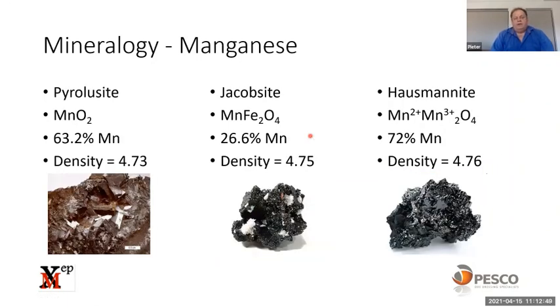Mineralogy for manganese is quite interesting. You've got 3 different types of manganese: pyrolusite, jacobsite, and hausmannite. What's interesting is there's a significant difference in the manganese content: 63.2% in the pyrolusite, 26.6% for the jacobsite, and hausmannite is 72%.